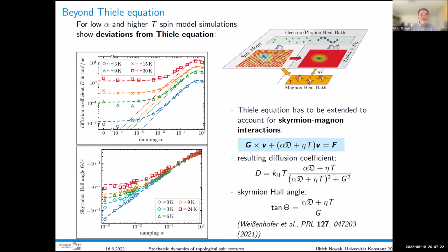And that is now a new solution of this extended Thiele equation with the magnon bath. And these are the dashed lines here in the graph. And now you see this agreement once again is perfect. So in other words, the Thiele equation is not sufficient to describe the coupling of magnetic texture to the magnonic heat bath, and so if you have many magnons, higher temperature or high coupling to that, or a low coupling to the other heat bath, a low alpha, then it becomes important.